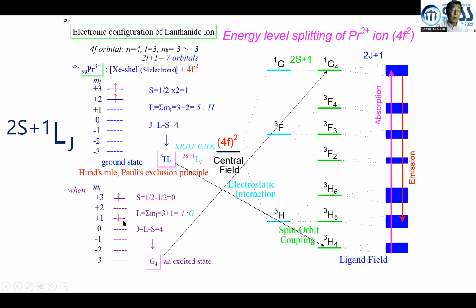If 1 electron is located like this, the total spin number becomes 0, and L equals 4, corresponding to the letter G, and the total quantum number becomes 4 minus 0 equals 4. This is called singlet G4, which is an excited state at 10,000 wave numbers, corresponding to a 1 micron wavelength. So the praseodymium ion can absorb a 1 micron photon and emit 1.3 micron photons, which is the wavelength of the second telecommunication window, the transition of the praseodymium-doped fiber amplifier.